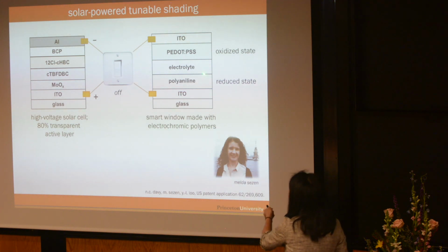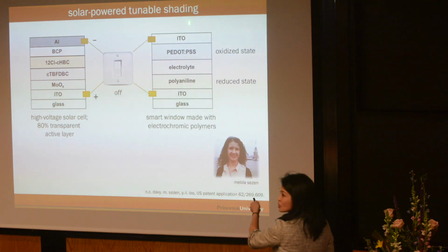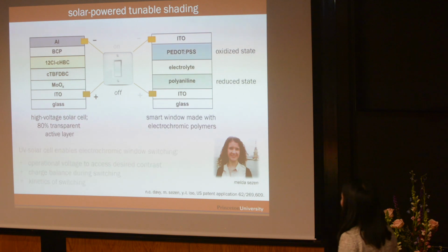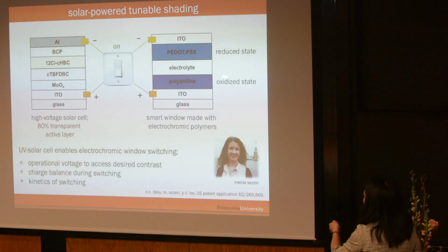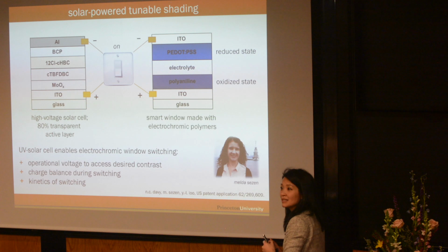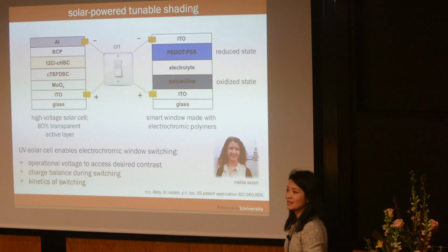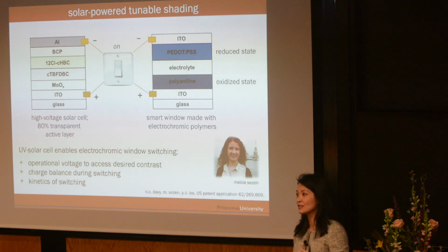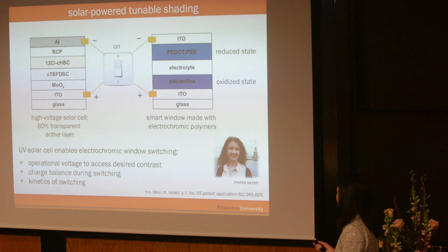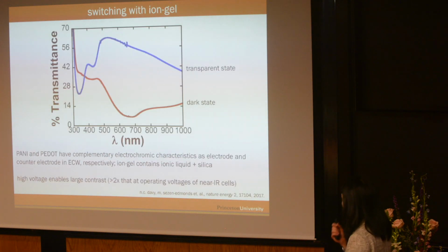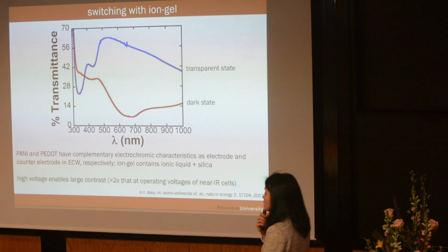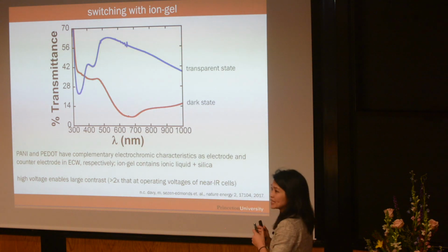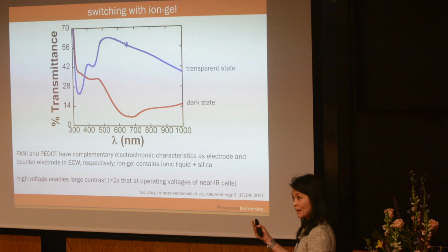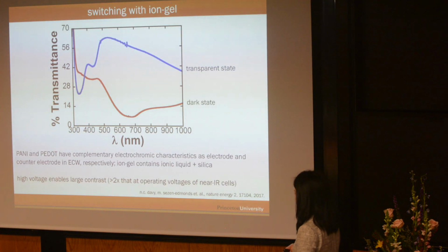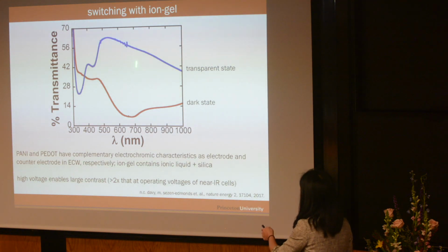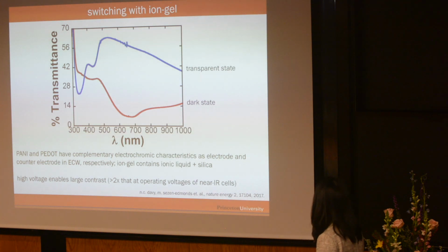You need the electrolyte, because you need a way to shuttle the electrons back and forth. And then, of course, when you want the dark state, when polyaniline is oxidized, PEDOT:PSS needs to be reduced, and both are in the dark state, so it enhances the contrast between the colored state and the bleached state of our electrochromic window. So this is to show you the contrast between the colored state and the transparent state of our window. This is, again, switched by our transparent solar cell now. And so you can see the contrast is quite nice in the visible range.